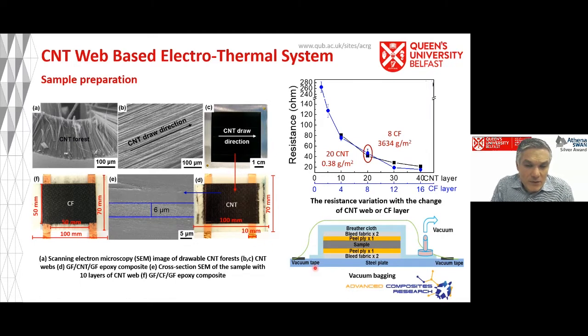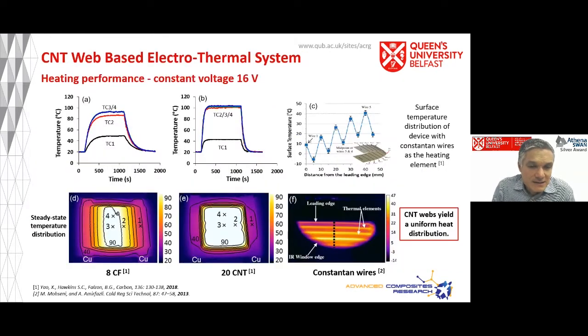And what I will also say is that because they are so light, they don't have much thermal mass. So the heat up rate for the carbon nanotube as a web, as a heating element, is much steeper compared to, say, the carbon fibers. As a comparison here, there was some recent work looking at Constantan wires, which is a copper and nickel alloy in a leading edge. And you can see there how the surface temperature is actually quite non-uniform because you've got these discrete elements. What you see here also is how uniform the heating distribution is with your carbon nanotubes as the heating element, even compared to the carbon fibers.